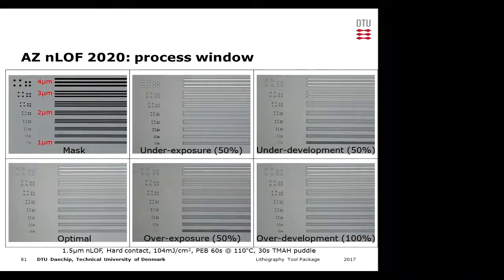And if we try the opposite and just develop for twice as long, so this is 1 minute development, you can see it looks really good. I can hardly tell the difference between this one and that one. So we don't actually have enough resolution in the image to tell us any difference.